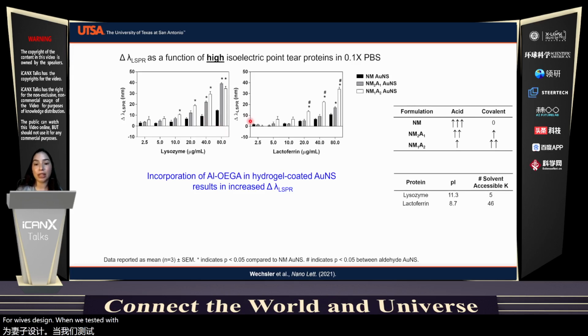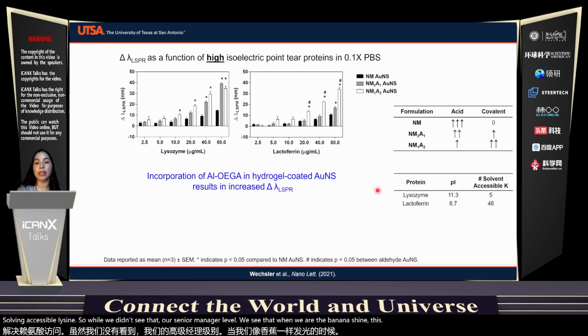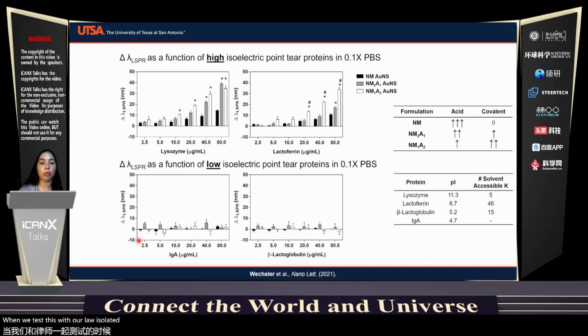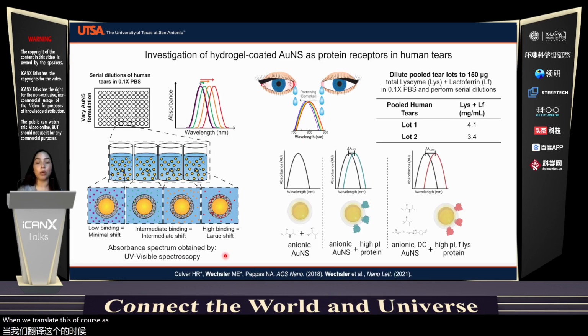When we tested with lactoferrin, this is when we start to see changes between the 2 formulations that contained our aldehyde component. And lactoferrin has more solvent accessible lysines. And so when we incorporate our signal transducing agent, this is when we start to see the differences in the use of our monomer that's able to form covalent bonds with our solvent accessible lysine. So while we didn't see that at the nanogel level, we see that when we add the gold nanoshell, and this is because once we add our gold into our sensor, that significantly increases the sensitivity of this sensor. When we test this with our low isoelectric point proteins, we observe little to no binding with our low isoelectric point proteins.